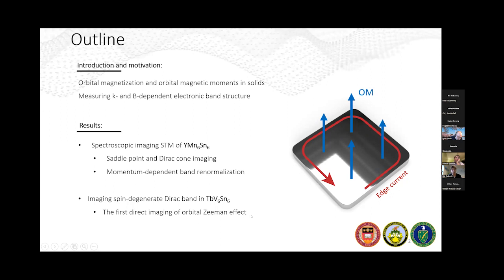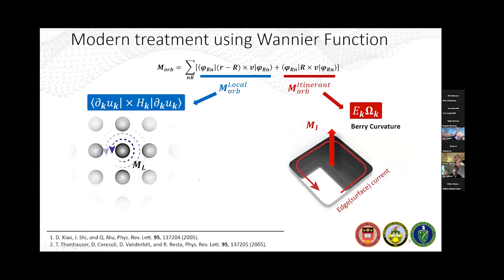And what we found in this system is actually very interesting. We were able to image one of the Dirac dispersions, and it turns out it splits in magnetic field quite substantially. What we'll try to argue is that this is due to underlying orbital magnetic moments that should generally occur in these kagome materials at certain portions of the electronic band structure.